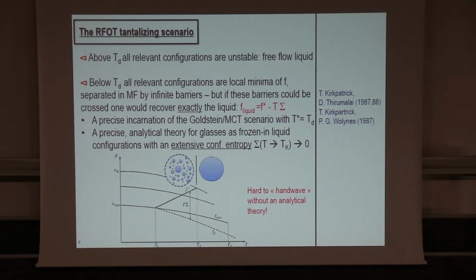So this suggests, compared to the phenomenology of glasses that I reminded you before, a tantalizing scenario that above Td, all relevant thermodynamical configurations are unstable. Locally, the Hessian has unstable directions, so it's a free flow, unencumbered dynamics. But below Td, at least in mean field, all the relevant configurations are local minima from which you can't escape because barriers are infinite. But if these barriers could be crossed, then one would recover exactly the free energy of the liquid. That is, the free energy of the liquid turns out to be exactly the free energy of these dominant states at a given temperature minus T times the log of their number. So it's really a precise incarnation of this Goldstein MCT scenario with a temperature T star equal to this dynamical transition, and also a precise analytical theory for glasses as just a frozen-in liquid in a very precise sense.